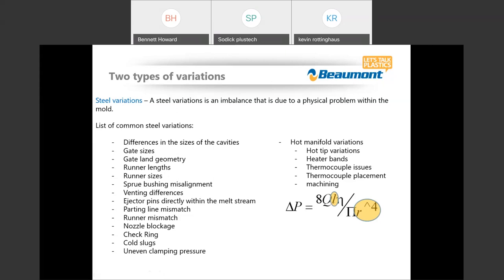And it's not necessarily a super bad thing from a balance standpoint, but sometimes during maintenance or over the life of the tool, a pin might break or be replaced with a different pin of a different size or a different length. And now we end up with variation side to side in a runner. So we oftentimes try to encourage people to get those out of the melt stream. Parting line mismatch, runner mismatch, nozzle blockage, check ring issues, cold slugs, uneven clamping pressure.